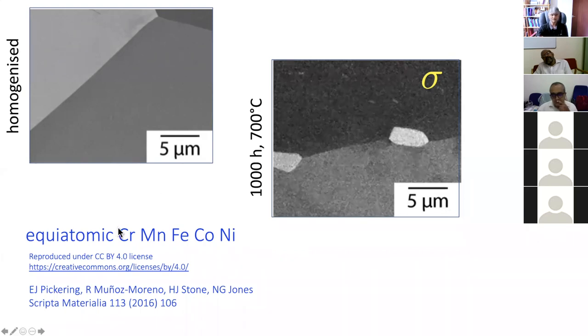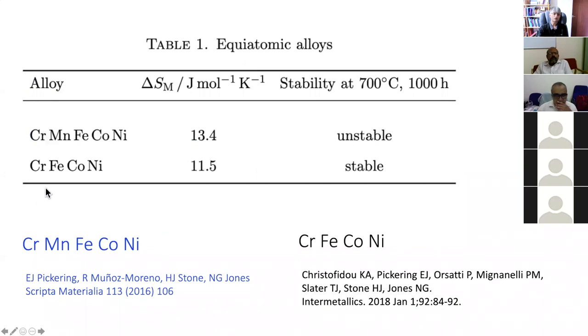And of course, this is the classic high-entropy alloy, where we have equal amounts of chromium, manganese, iron, cobalt, and nickel. But there are other variants of this so-called Cantor alloy, and the chromium, iron, cobalt, nickel with equal amounts of each of these elements has a lower entropy of mixing because there are four components as opposed to five. And yet, if you anneal this for 1,000 hours at 700 degrees centigrade, it remains stable. Okay, so in terms of stability with respect to sigma phase, this is considered to be unstable, and this is considered to be stable, even though this has a lower entropy of mixing.